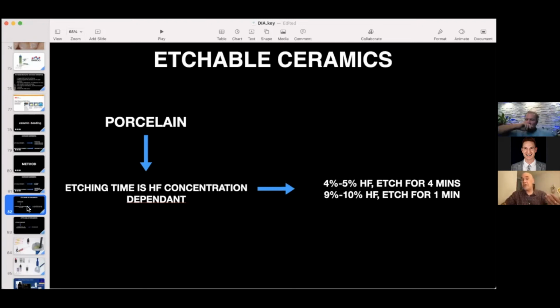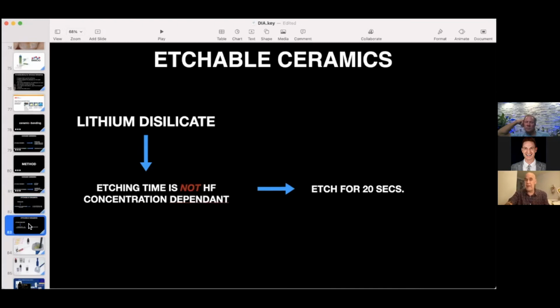If you're going to etch your feldspathic porcelain with hydrofluoric acid anywhere between 4 and 5%, you're going to have to etch it for 4 minutes. Now, if you have a hydrofluoric acid whose concentration is between 9 to 10%, you can etch it for 1 minute. So the concentration of your hydrofluoric acid will have an effect on your etching time on feldspathic porcelain. On lithium disilicate, it doesn't matter.